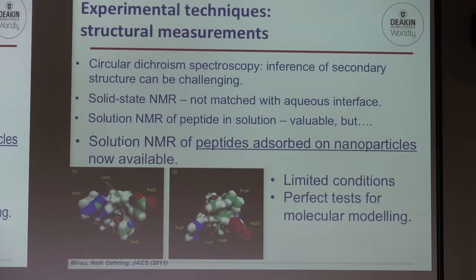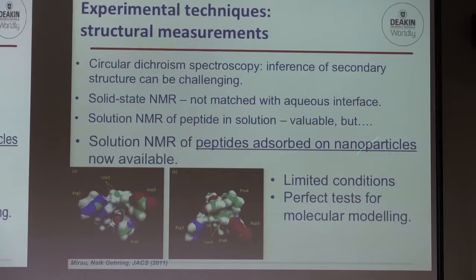But recently, some teams have been able to carry out and interpret a different kind of NMR. If you're not familiar with NMR, it just tells you something about the structure of these molecules. So we can determine something about the structure when they're adsorbed onto the inorganic material. But it can only be carried out for limited conditions, so we can't just be applying it everywhere in all cases, unfortunately. But for the cases where it is possible to carry out the experiments, this is a perfect test ground for molecular modelling, because it enables us to confront our structural predictions with what is being measured.